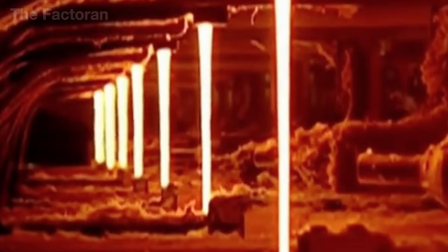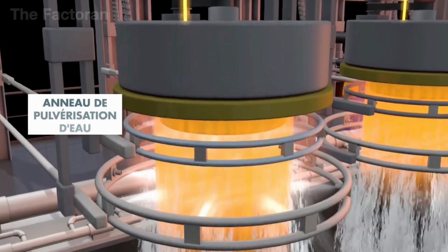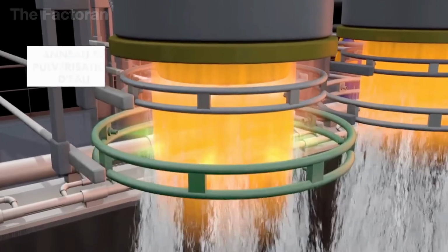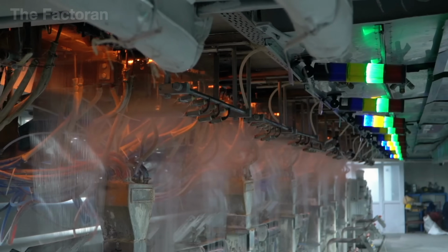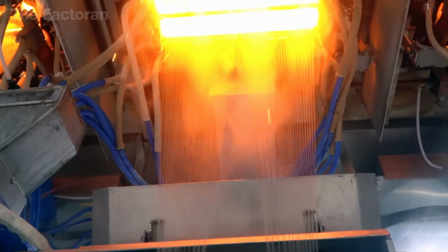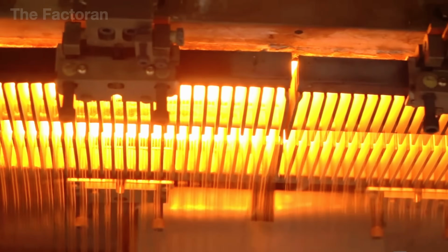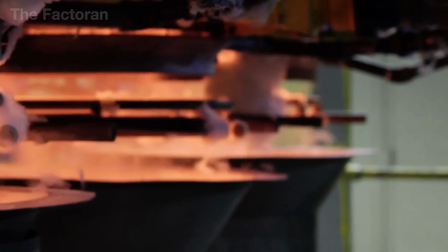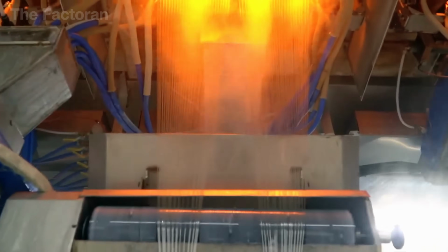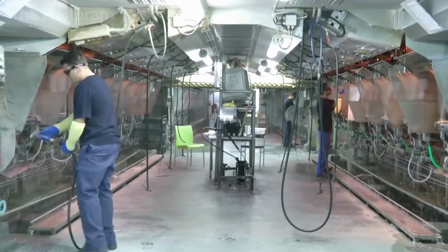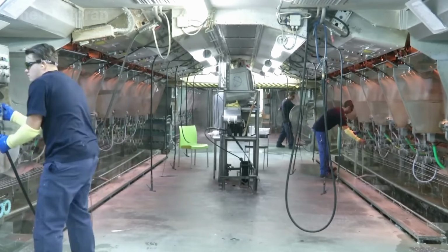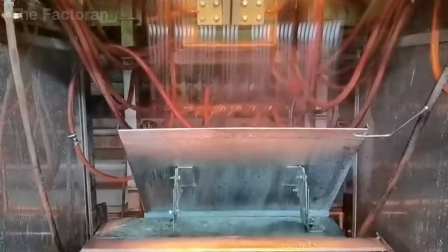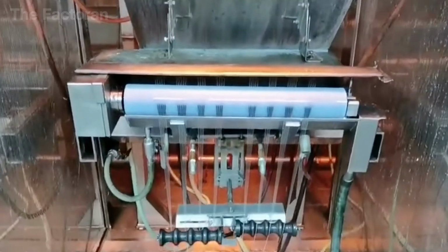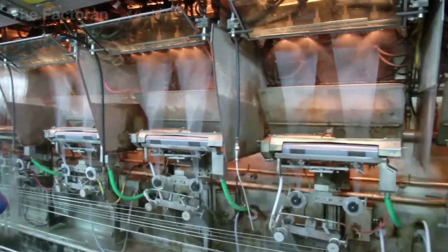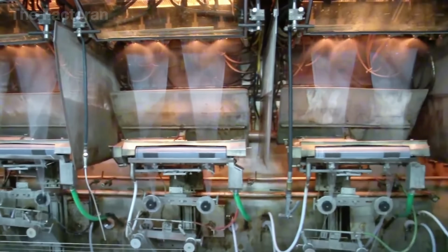As the molten glass flows through the tiny holes, gravity and mechanical pulling transform it into filaments as thin as a strand of hair. Each measures only about 5 to 25 microns in diameter, much thinner than human hair, yet incredibly strong. Thousands of fibers are drawn simultaneously, forming a glowing stream under the intense heat. One fascinating aspect of the entire plant is that it must run continuously, 365 days a year, because if it stops, the fibers solidify into a hardened mass that can damage the equipment.